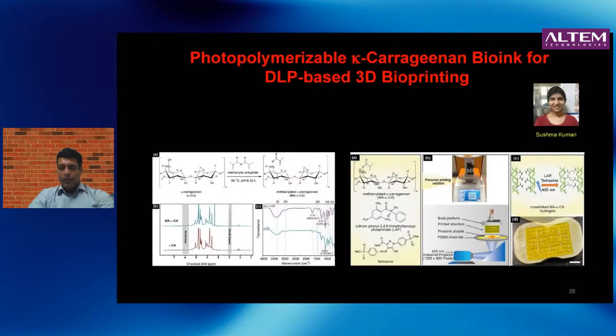In another approach, and this is work of another postdoctoral fellow, instead of using a protein-based polymer, we used a carbohydrate or a polysaccharide-based polymer. Here again, we modified it so that it's got an acrylate group, and we've done all the chemical characterization that yes, indeed, we have introduced the acrylate group. And then what we do is we can add a photo initiator in it, and then we do again this bioprinting.